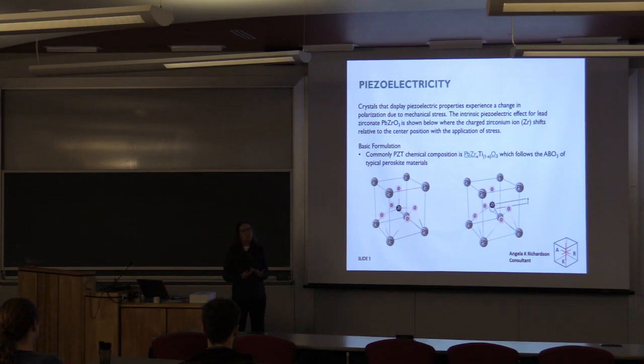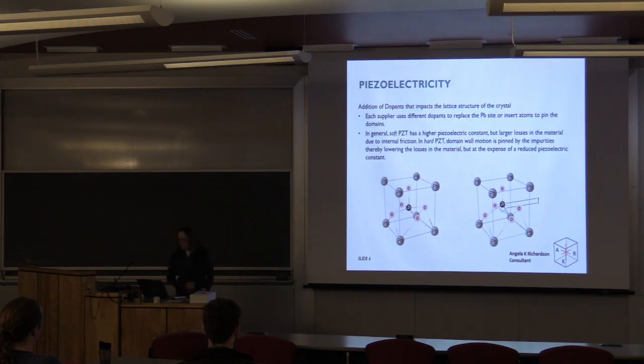So when we think about piezoelectricity, what we think about is a ceramic structure, that perovskite structure that basically is of an ABO3 configuration. So you have the lead on the corner of the lattice, you have the oxygen face-centered, and you have that zirconium in the center. And it could be titanium too. So the reason you have the ability to create a voltage is the movement of that zirconium atom. Okay? You can add other dopants to this constituent, but depending on what additives you add to that crystal structure, you'll get different electrical properties. Okay?